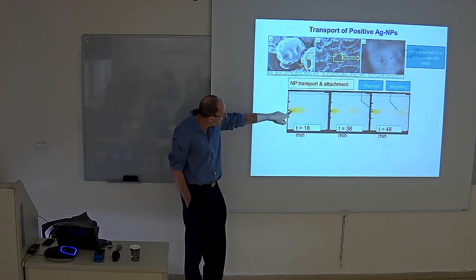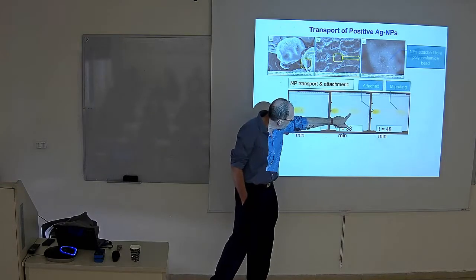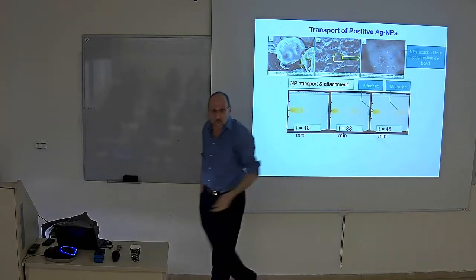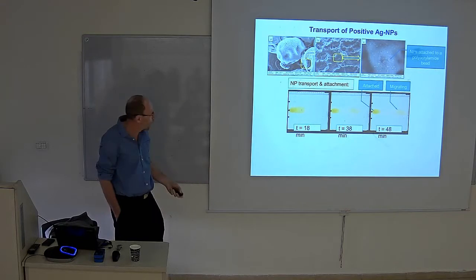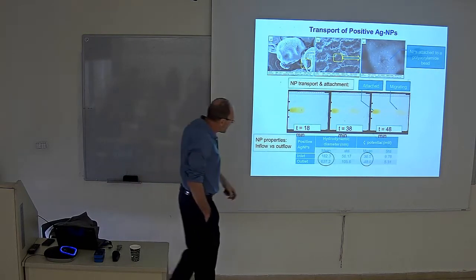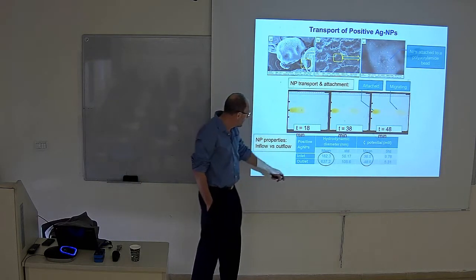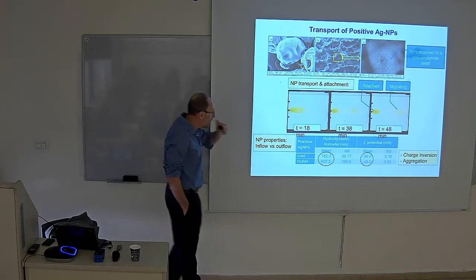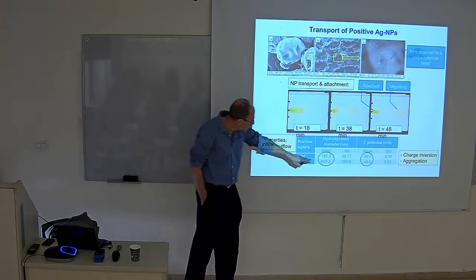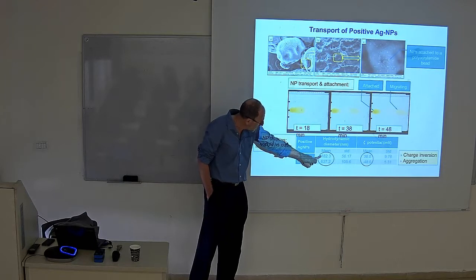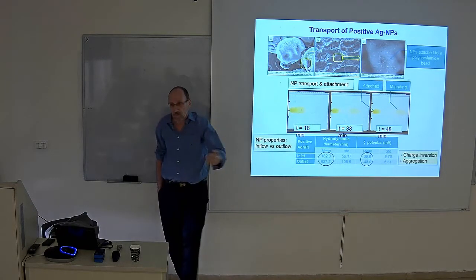You can see here the vast majority of them are captured, as you would expect. But we noticed after half an hour, there's actually a plume here. Some of the material is actually becoming mobile. What's going on? Now, if you look at the zeta potential and the diameter of the particles, at the inlet they were 182 nanometers in diameter, and by the outlet, they're 3-4 times the size.